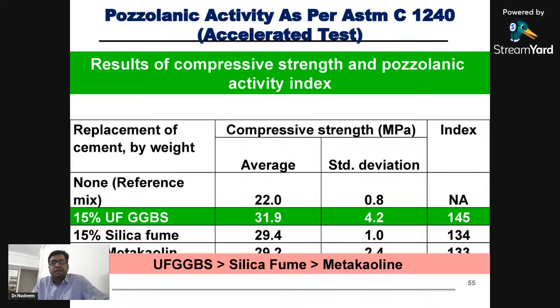Coming to pozzolanic activity as per ASTM C1240, here cement is replaced with 15% of various microfine materials. So this is ultrafine GGBS or Alccofine, silica fume, or metakaolin, and its strength is checked with reference to the reference mix. The reference mix gave 22 MPa. Against that, Alccofine gave around 32 MPa, silica fume 29 MPa, and metakaolin also around 29 MPa. So these are the tests conducted to know the pozzolanic activity as per ASTM.